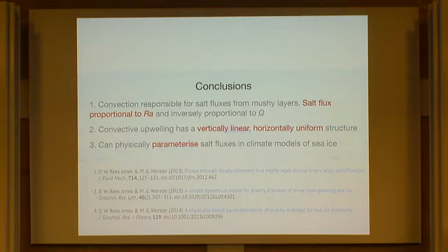Neil? Yeah, the permeability of sea ice must be anisotropic? What would be the difference? There haven't been many attempts to measure this. People think that the top layer of sea ice is often formed in a turbulent environment and has a granular texture, so in that region it's reasonable to assume it's fairly isotropic. But lots of sea ice has this, as we saw at the bottom of the piece of sea ice, where you can see the ends of plates.